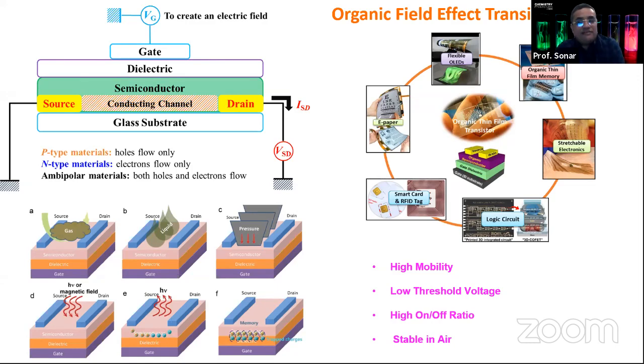Whereas in the case of an organic field effect transistor, using some of our organic materials, we can reach a switching value close to 10 raised to 5, 10 raised to 6, and then we can consider this really a very good switch. So this transistor can be utilized for various purposes. First of all, we can expose this channel semiconductor to a gas as a sensor, or might be a liquid. We can put a pressure on this semiconductor, and then we can take a dielectric, might be a rubbery or soft material there. We can act as a pressure sensor.